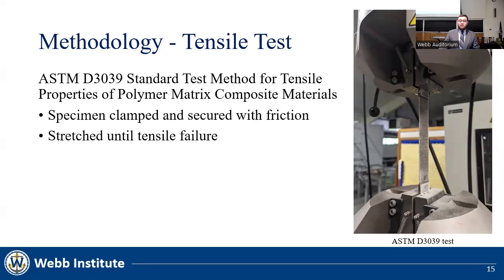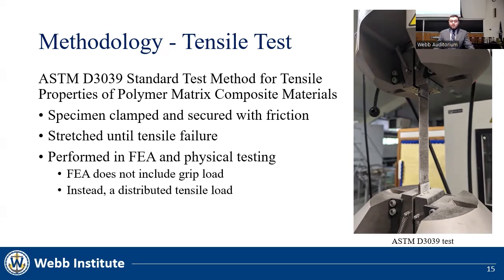It is a basic test to determine tensile properties where the specimen is clamped and secured with friction and stretched until tensile failure. The FEA model does not model the compressive force of the grips onto the composite, but it does use a distributed tensile load over the same length as the grips. This simplifies the model as the compressive load does not make a significant difference on the overall breaking stress. The ultimate goal of this test is to find the ultimate tensile strength.